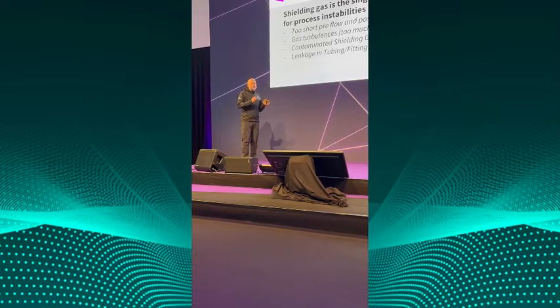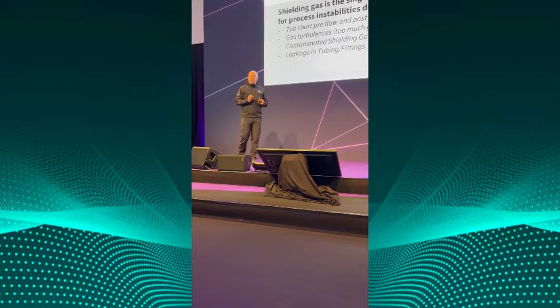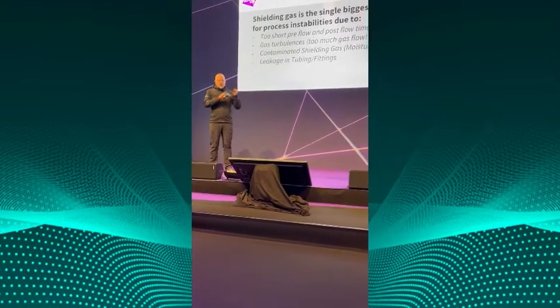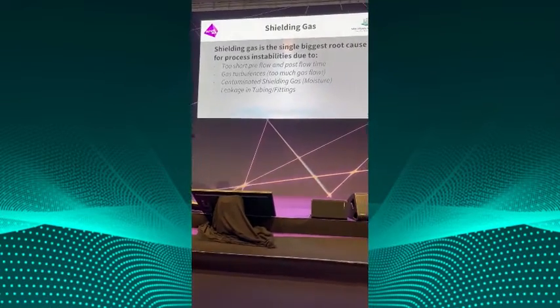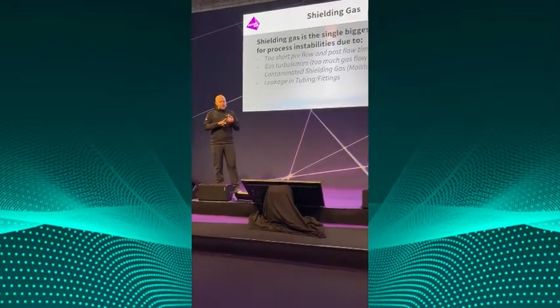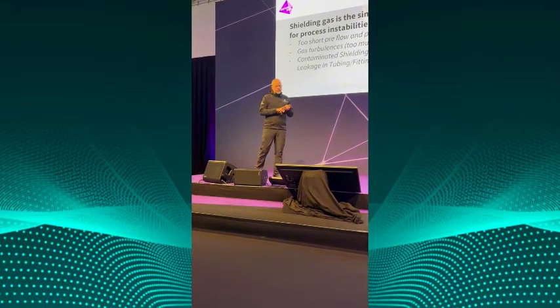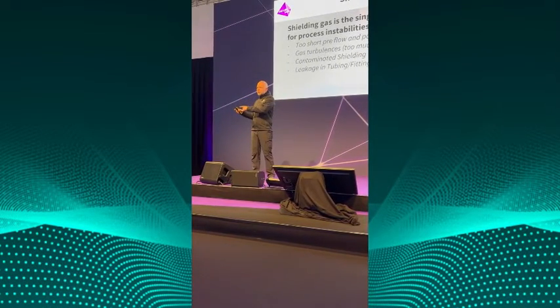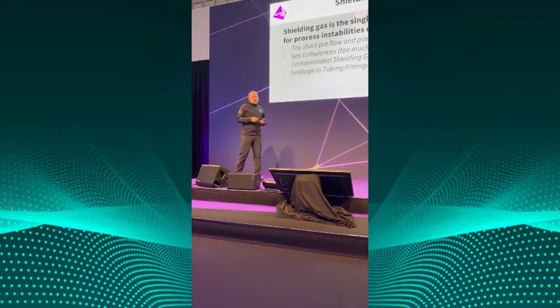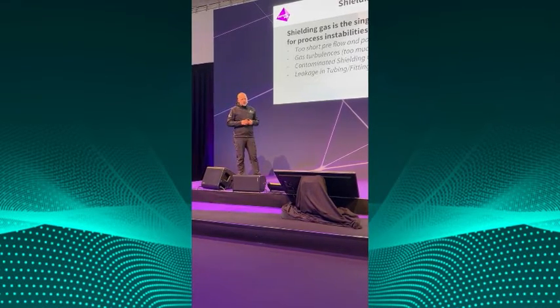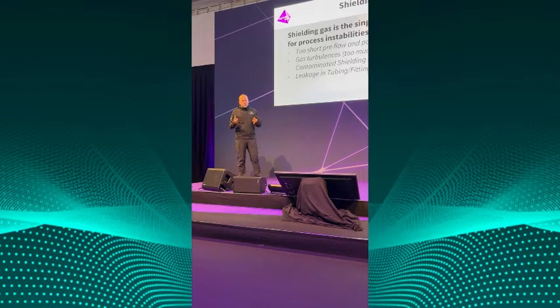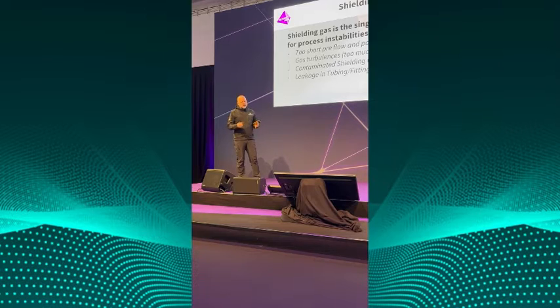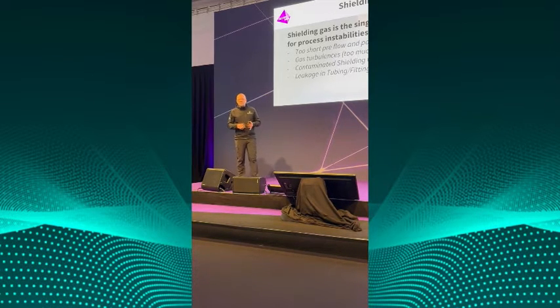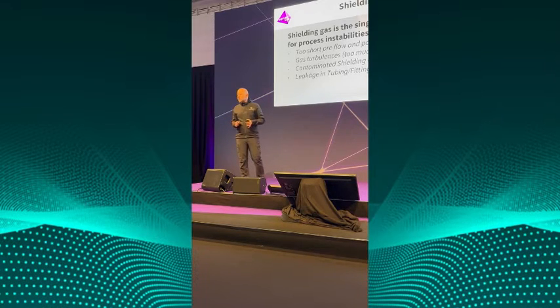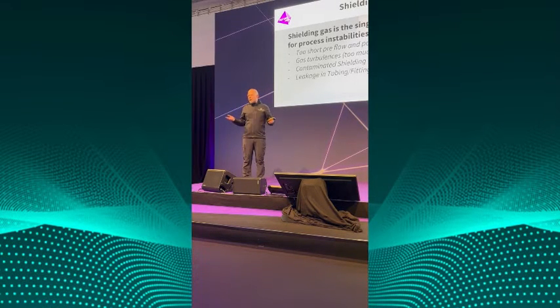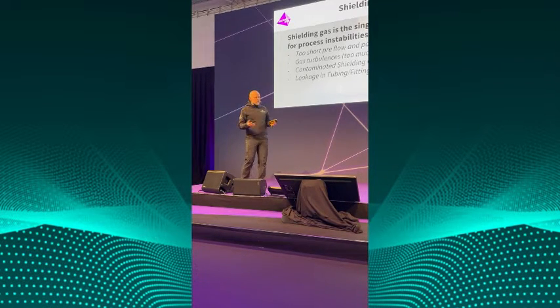But shielding gas is also the single biggest root cause for process instability, and this is due mostly to too short pre or post flow, gas turbulences, and in almost all cases, gas turbulences are caused by too much shielding gas. Contaminated shielding gas, especially trace moisture, is one of the biggest issues because it's super hard to detect. And of course, leakage in tubing fittings is causing, in the industry, I would guess, annually multi-millions of lost revenue, rework, just unnecessary work or expenses.